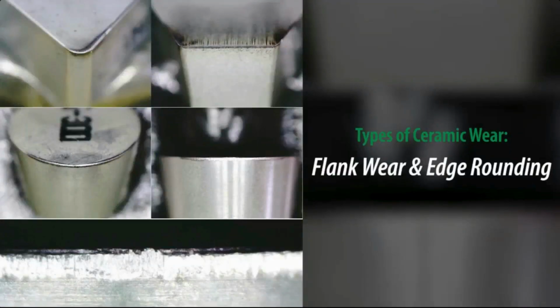Aaron and Martin, can you expand a little bit on some of the wear that you might run into with ceramic tooling and what it means? Sure. So the first type of wear we have is flank wear and edge rounding, otherwise referred to as regular wear. It is the best kind of wear to have. It means that the machining process is stable, the stresses are carried out well, the heat distribution is neither too little nor too much in either the tool or the workpiece, and the tool is being used up as efficiently as possible while material is being removed.